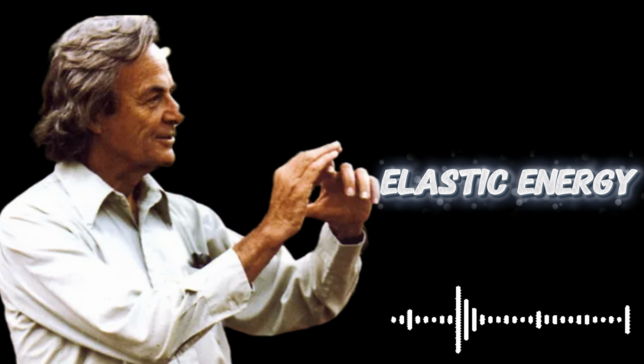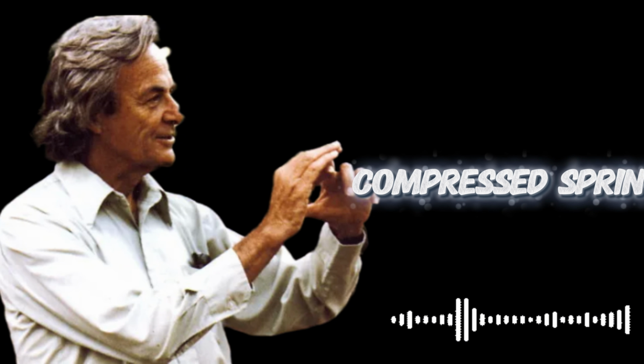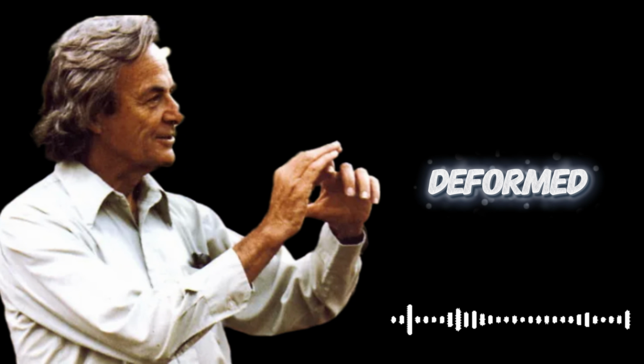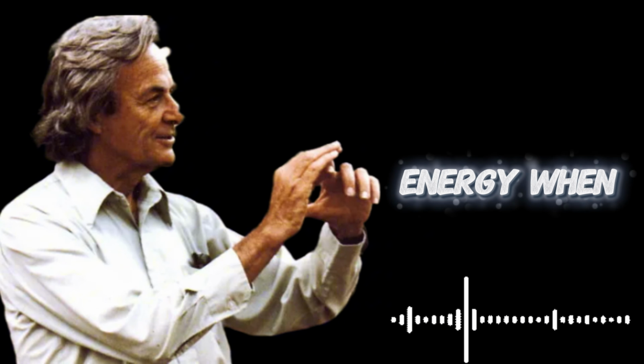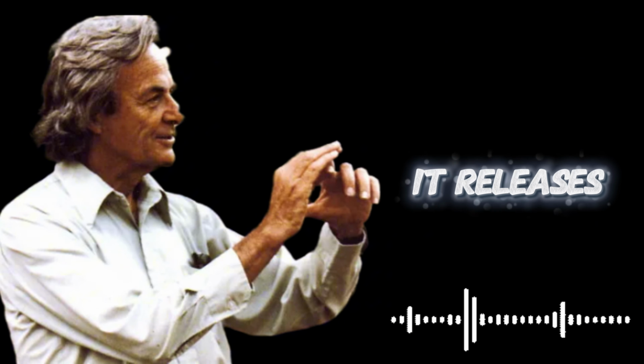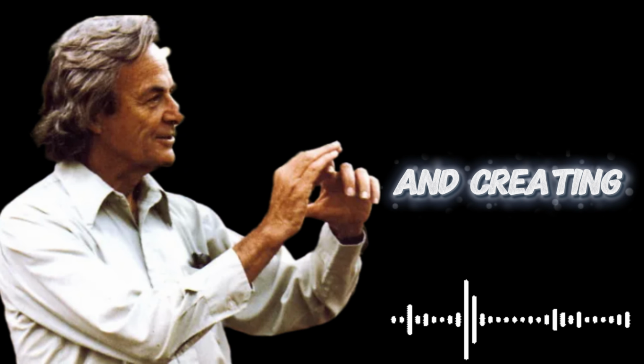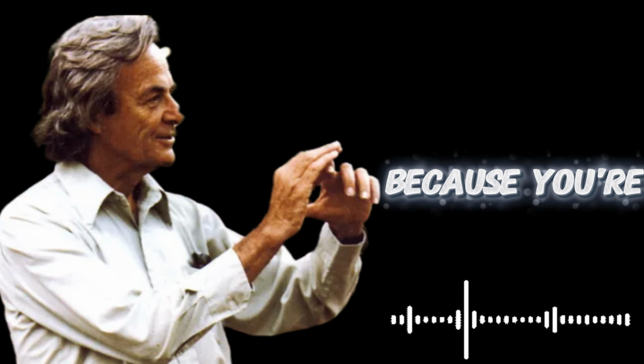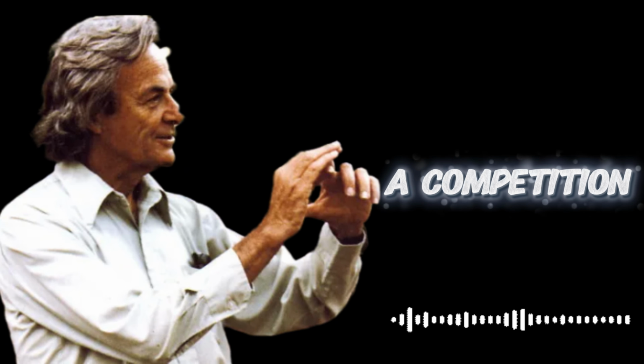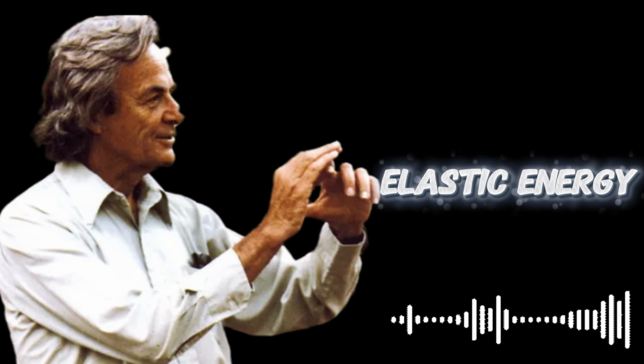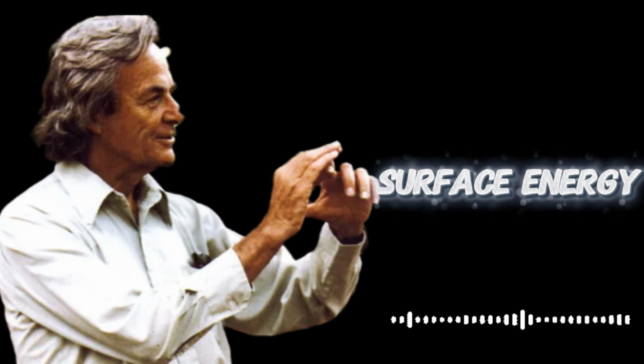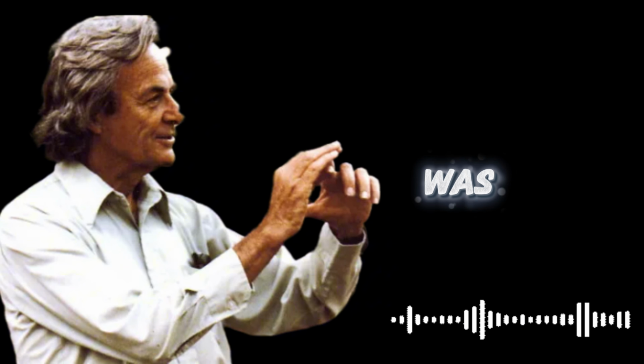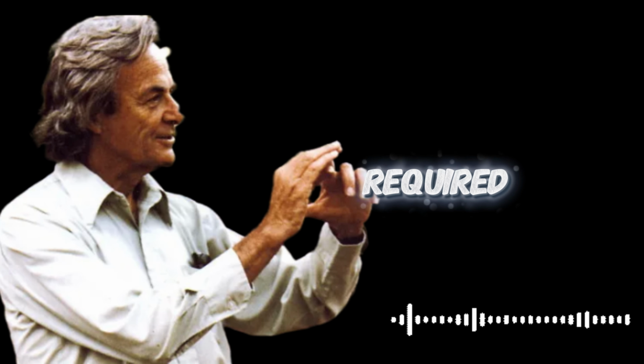This is crucial for understanding fracture. You have a piece of glass under stress. It's storing elastic energy like a compressed spring. The material is slightly deformed, and that deformation stores energy. When a crack grows, it releases some of that stored elastic energy. The crack creates new surface area, and creating surface requires energy because you're breaking bonds. So there's a competition. Growing the crack releases elastic energy, but requires surface energy. Griffith's brilliant insight was that a crack will grow when the released elastic energy exceeds the required surface energy.